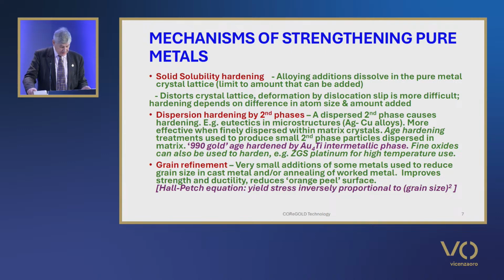The degree of hardening depends on the relative difference in atom size of the pure metal and the alloying metal, as well as the amount that you add. Thus, in carat golds, it is well known that copper is more effective than silver in hardening gold, as its atom is about 13% smaller compared to silver, which is only slightly larger than the gold atom.